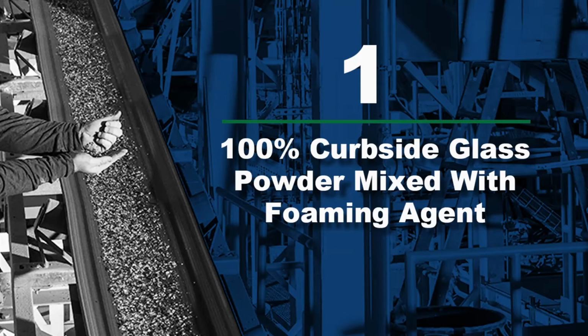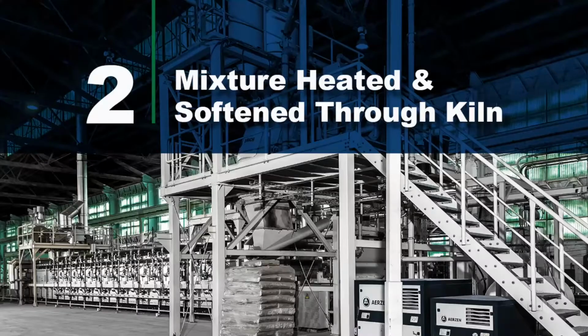All right, so we do that in the batch plant. It drops down into the mixer. And then once those two powders are mixed, it drops onto the belt of the kiln. All right, so this powder mixture is screeded off to be a consistent height right around 20 millimeters. And then it starts to go through the kiln. And inside of the kiln are, I think we have 13 or 14 different unique temperature zones.